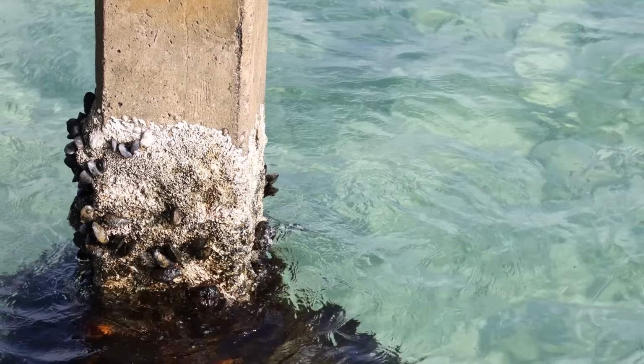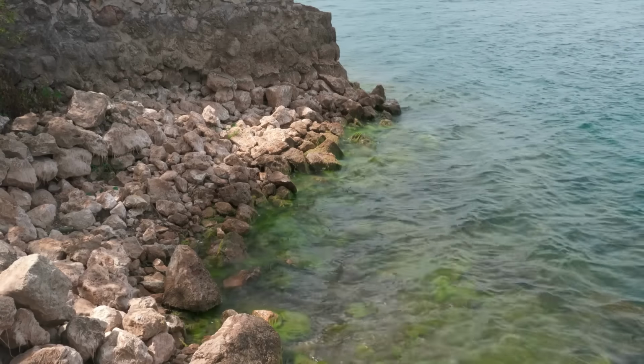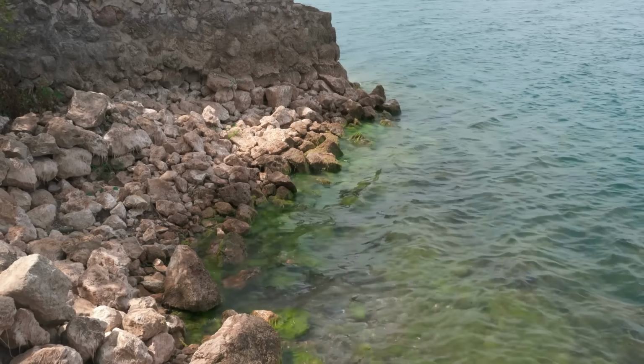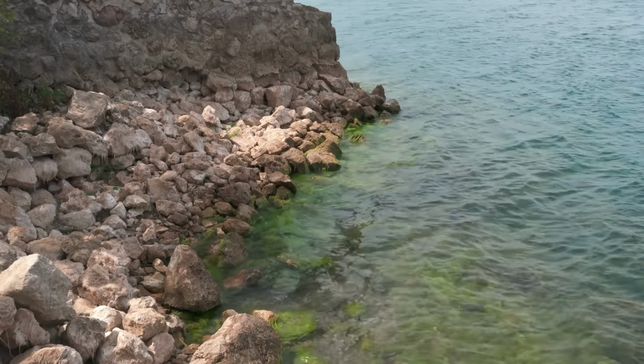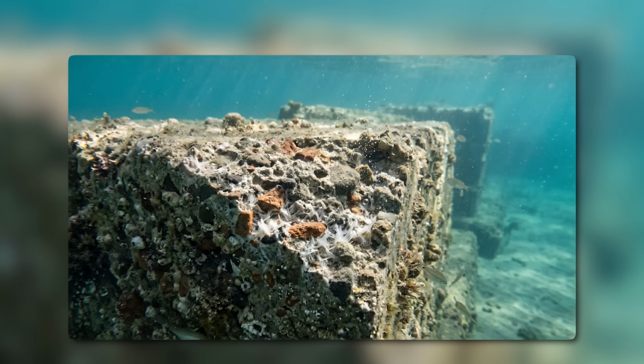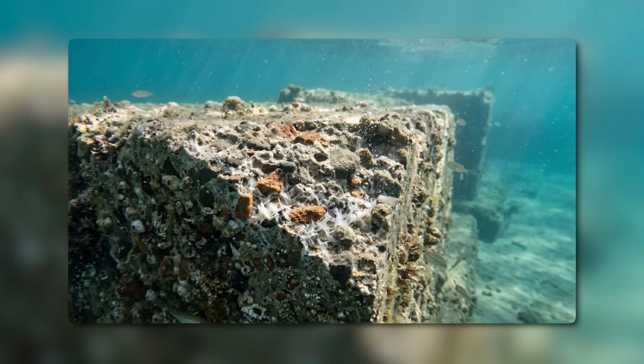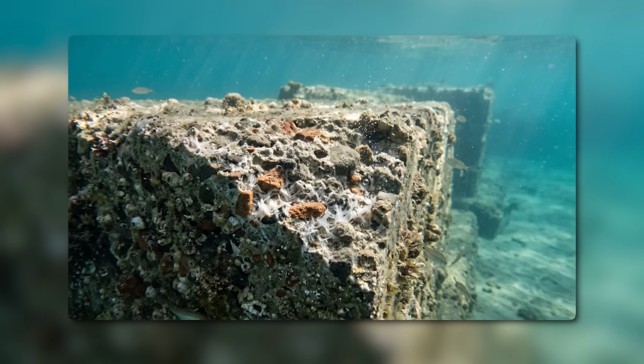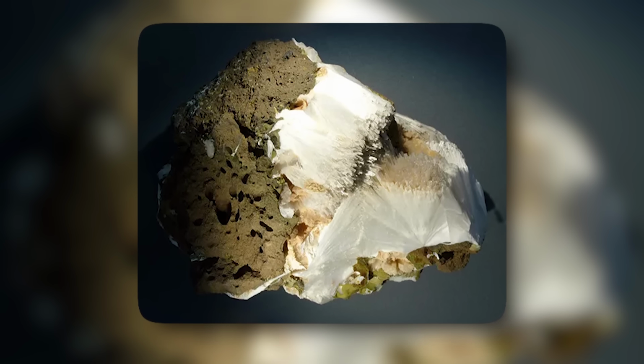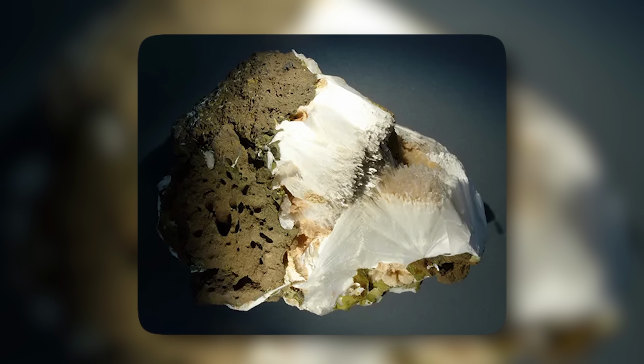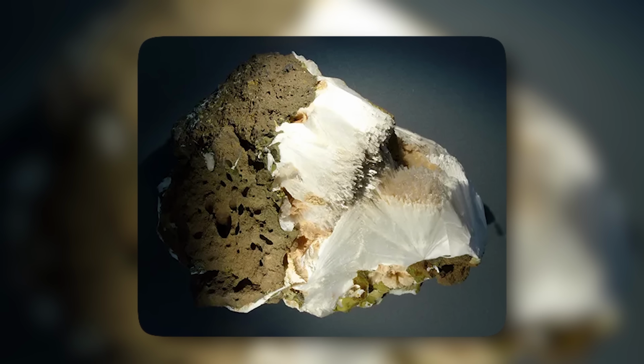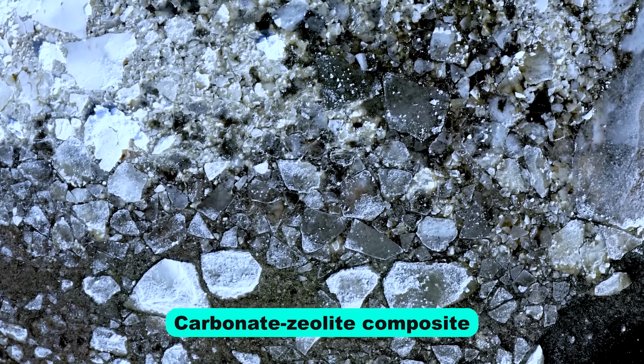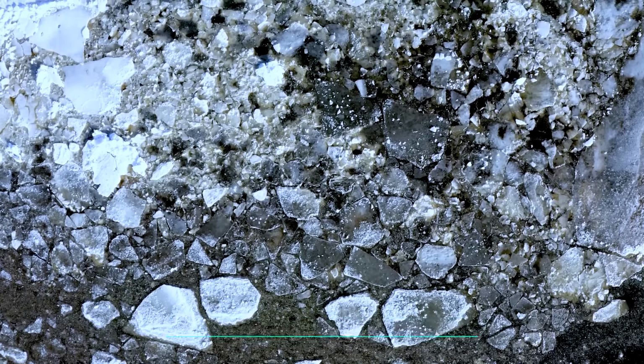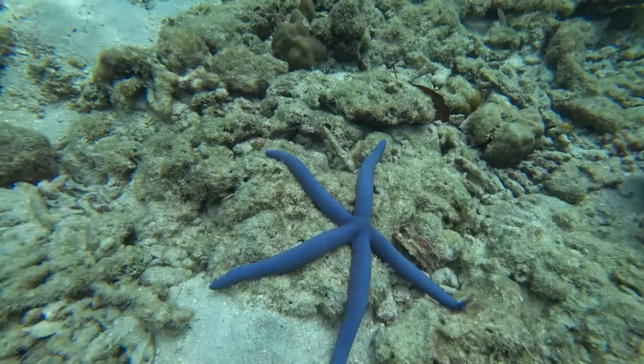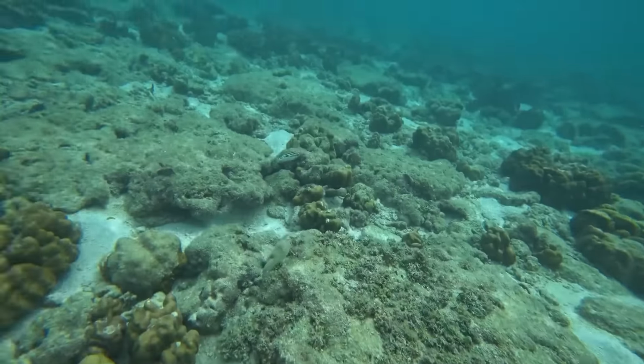They strengthen the concrete. Second, over centuries, the seawater continues to react with the lime in the matrix. Phillipsite, a zeolite mineral, grows into every microfracture in the concrete. Phillipsite pulls salt out of the seawater and locks it into the structure. The concrete becomes a carbonate zeolite composite that gets harder and denser every century it stays wet.